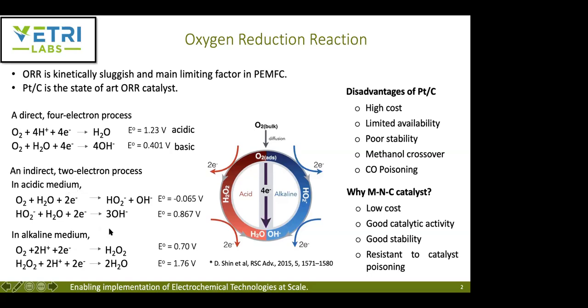So it has peroxide, and that peroxide, before diffusing into the electrolyte, gets converted back into water. So it's an indirect 2-electron process. And there are some catalysts that cannot go past this peroxide state, and they basically do a 2-electron oxygen reduction reaction.